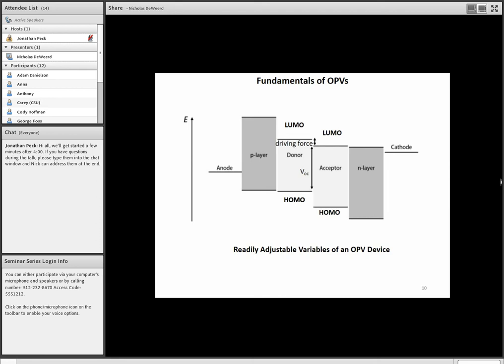So as chemists, one of the really easy things for us to change is this VOC gap between the HOMO and the LUMO of the donor and the acceptor. That's actually dictating our total VOC. Now, in different morphologies, you're actually going to see the HOMO and the LUMO energies change a little bit. And you can tell because, based on calculations, you know what your HOMO and LUMO gap should be. If you see your VOC is a little bit smaller, or even a little bit higher is also possible, that's usually due to differences in morphology.